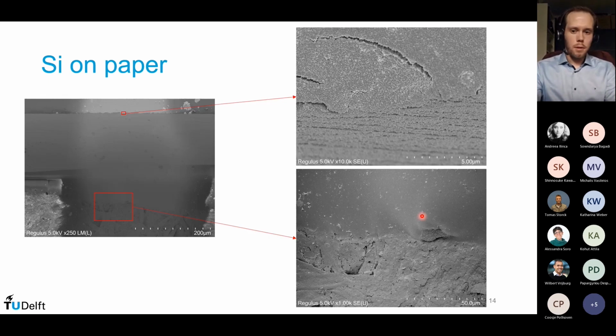So for silicon on paper, we see very similar behavior. At the top edge, of course, it's identical to the silicon on silicon samples. So we see good conformity with successful crossing of the top 90-degree corner. And at the bottom, we also see a good transition from the glue to the paper. So this is all coated very uniformly with the gold nanoparticles. You can even see that the fibers themselves are coated with very high conformity of the particles.